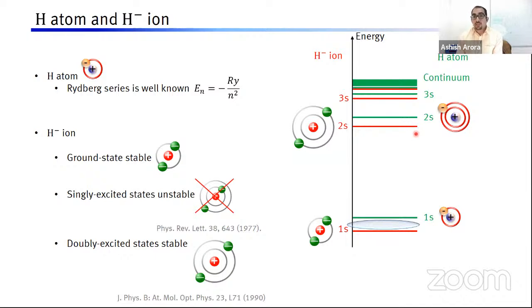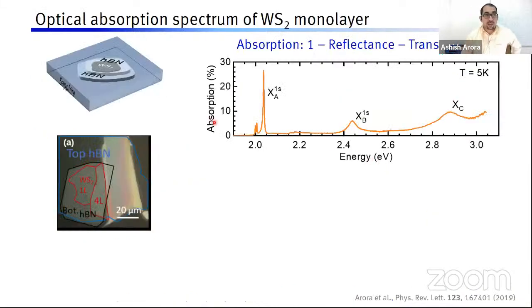Now we wanted to see if such a thing is possible to observe in solids as well. So we try to find these in monolayer transition metal dichalcogenide. We choose tungsten disulfide, which is encapsulated between thin layers of hexagonal boron nitride, which is an insulator. This is our sample structure where hexagonal boron nitride is encapsulating a monolayer of tungsten disulfide, and we measure its absorption spectrum by measuring reflectance and transmission in the same conditions.